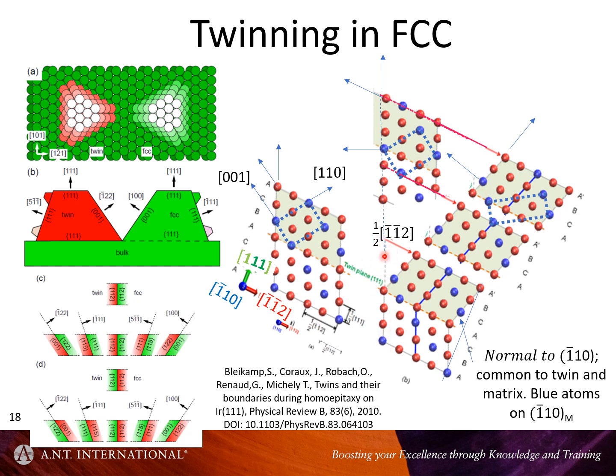And the twin shear occurs over 3 planes, 1, 2, 3, and by the time you've moved from there to there, the displacement you've taken is a half 1-1-2. Not going to go into too much detail. The mechanism is well understood, makes total sense, very easy to demonstrate with a ball model. But it produces a whole bunch of different orientations. There's only a few that are common to both the twin and the matrix, and only a few which have some rational relationship.